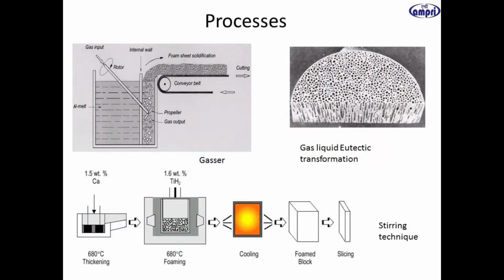The hydrogen gas gets entrapped within the metal, and it will give you bubbles, and you will get the metallic foam. Here you add calcium, which is added to control the viscosity of the melt. Instead of calcium, you can use other ceramic materials also, even fly ash or cenospheres, which can also be used as a thickening agent to control the viscosity of the melt. In that case, this material will be very cheap compared to other foams, because fly ash and cenosphere are not costly.